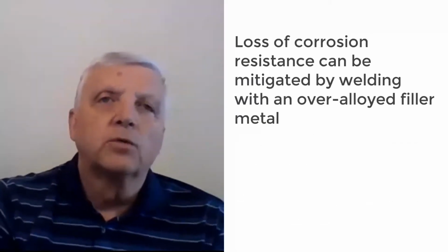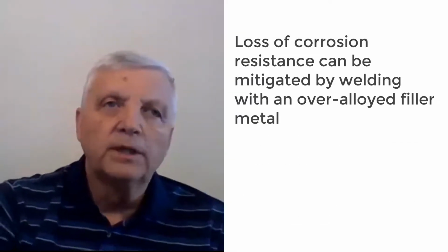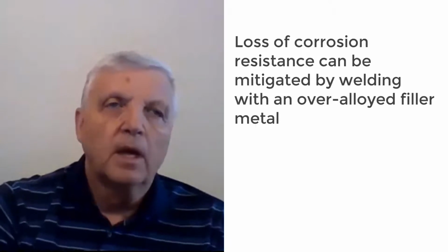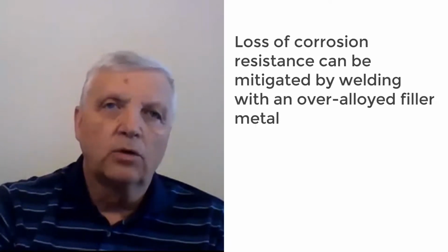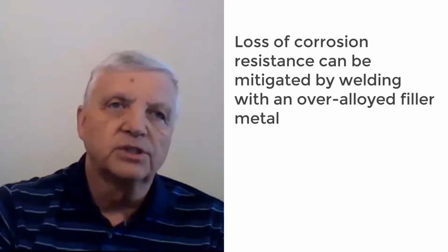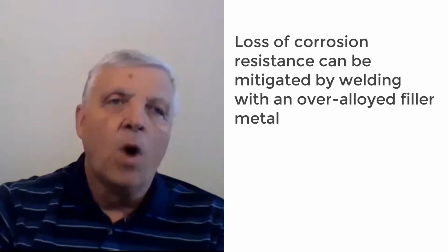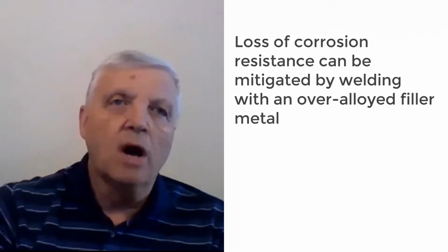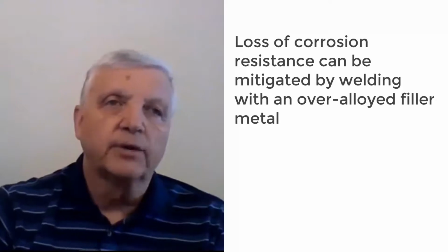The potential loss of corrosion resistance can be mitigated by welding with an overalloyed filler metal. Thus, weld metal produced with an overalloyed filler metal can possess corrosion resistance equivalent to the starting base metal, while the autogenous weld metal will possess compromised corrosion resistance due to segregation of alloying elements.